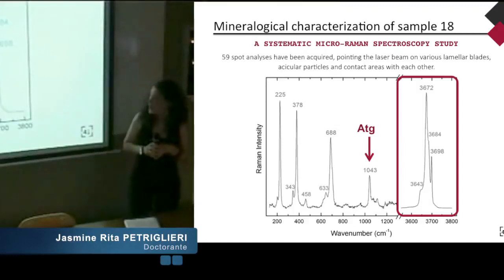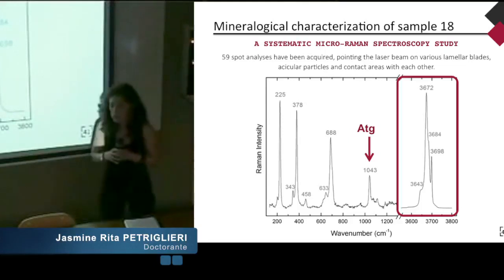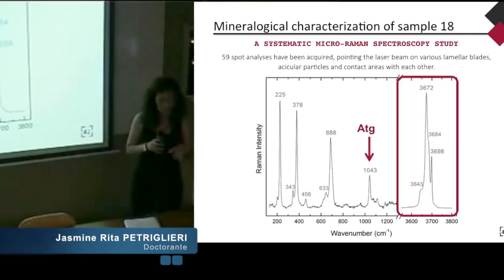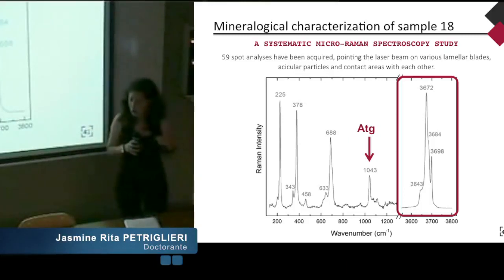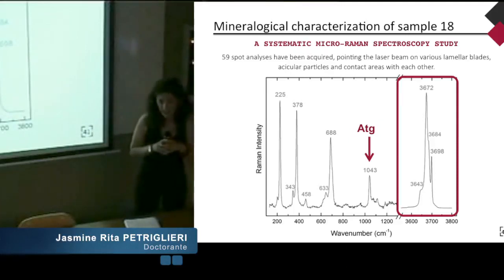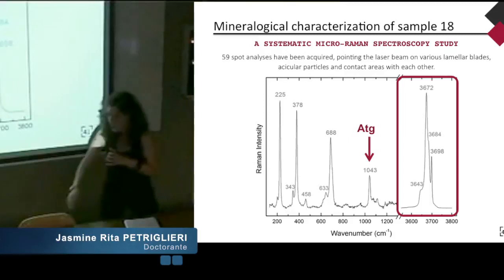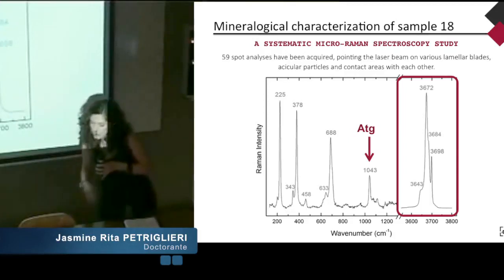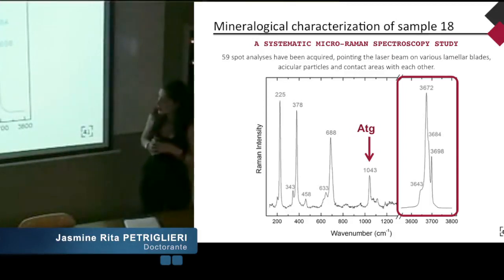For this reason, we decided to use micro-Raman spectroscopy to investigate the different mineralogical assemblages on the thin petrographic section, and about 60 spot analyses have been acquired, pointing the laser beam on various lamellar blades, particles, and at the area in contact with each other. All 60 spot analyses are perfectly comparable, and the lower wavenumber region shows the typical Raman spectra of antigorite.